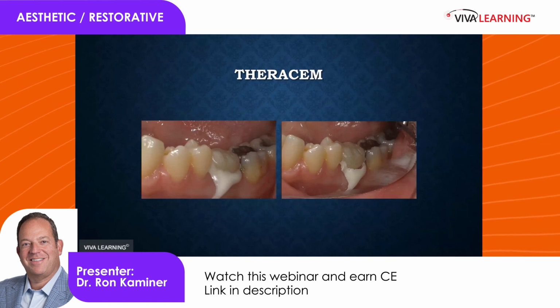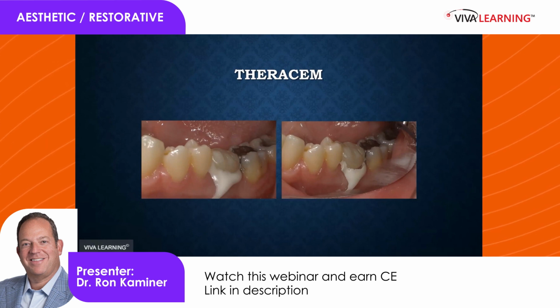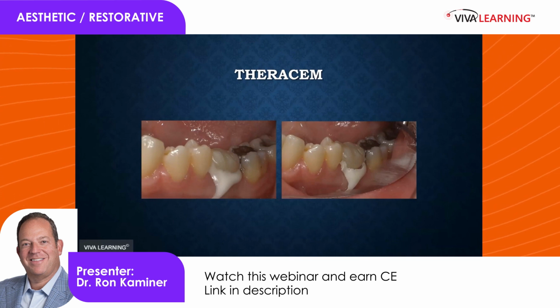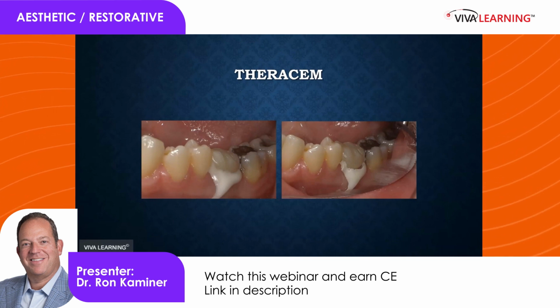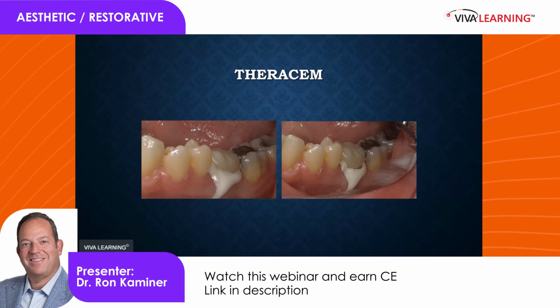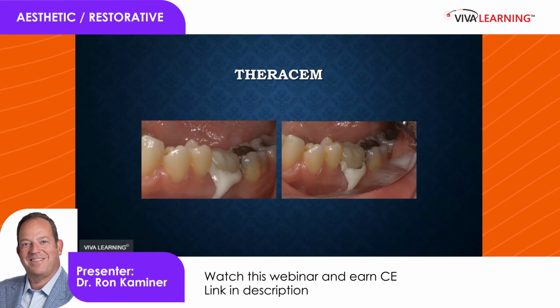What you see here is when I compress the crown into place, the Theracem is flowing on all sides. I hit it with the light for about 5 or 6 seconds, and now I'm getting a tack cure component. If you look here on the right, the so-called gel state, you can see that I've teased it away from the margin with the explorer just to show you how it's going to peel off in one step. I'm then going to take my floss. I'm going to floss in approximately.